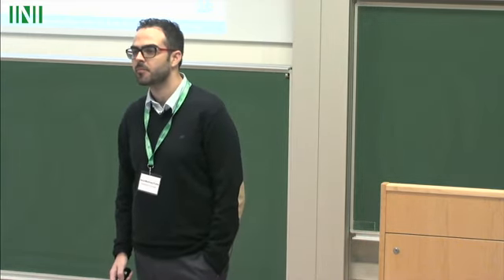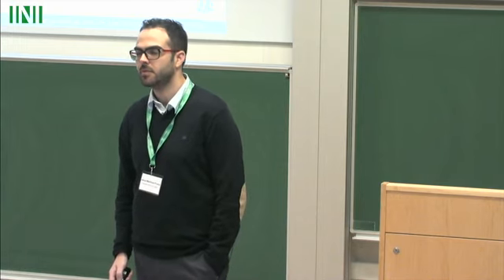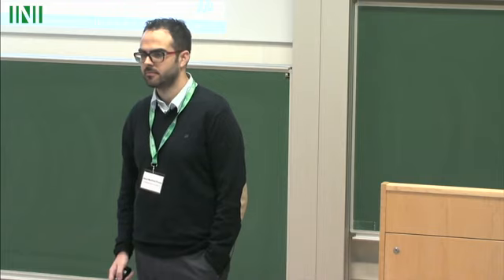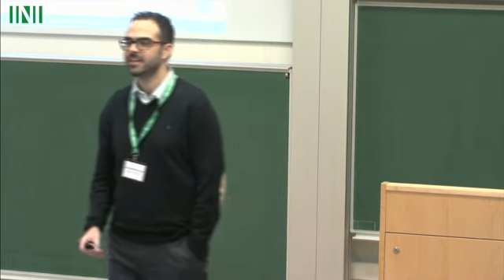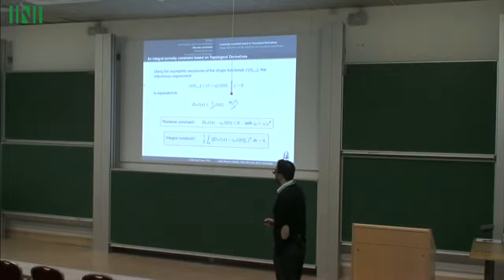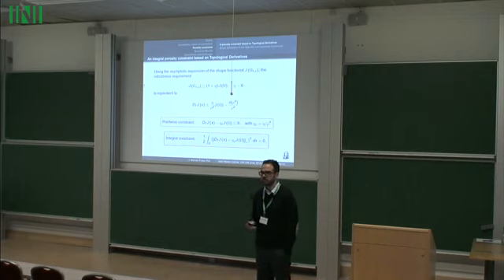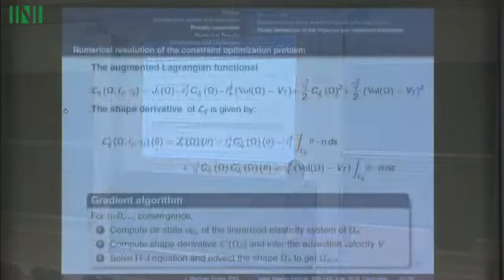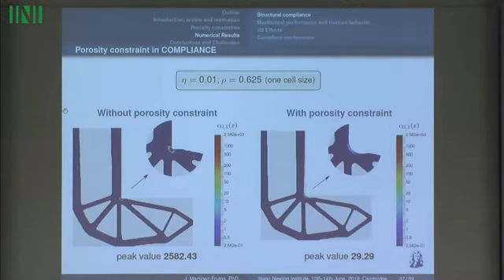Yes, back there. Go ahead, please. Yeah, so now the size of your hole is dependent on an element in the mesh, right? Yes. Did you do some convergence studies where you sort of increase your... No, I just take the smallest element as the radius of the porosity. I would just be interested, if you take a twice finer mesh and then take a hole which is 2 elements, do you see the same result? I don't expect the shape to change, because when we change this porosity constraint in compliance and we change to stress, the effect is quite similar. So I don't expect that refining the mesh would give something different in this example, because the problem is very local here.